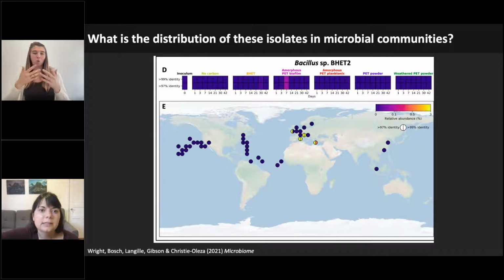We also find Bacillus in some of our community samples, although we typically find it to be of really low abundance. And we only really find it to be abundant on one day, day 7 of our amorphous or low crystallinity PET samples. And we also found that in the other plastosphere studies, it was really only present in European plastic samples, but in one of these, it did make up 25% of the community.